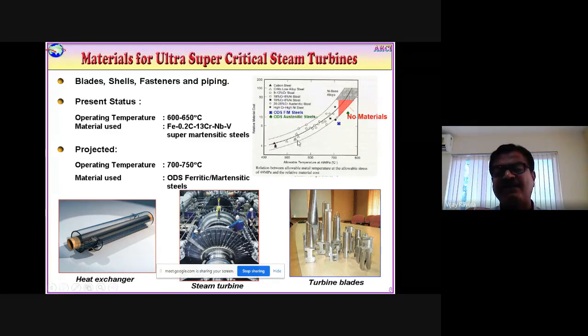If you look at this graph, this is the relative material cost with steel versus allowable temperature, and there is this red gap. There is no material available, so people have to use nickel-based alloys, where the cost goes up by 50 times the steel cost. When we develop these ODS ferritic martensitic or ODS austenitic steels, the cost will be here, and they can be used for turbine blades in thermal power plant applications. So in this regard, we have been developing those materials.